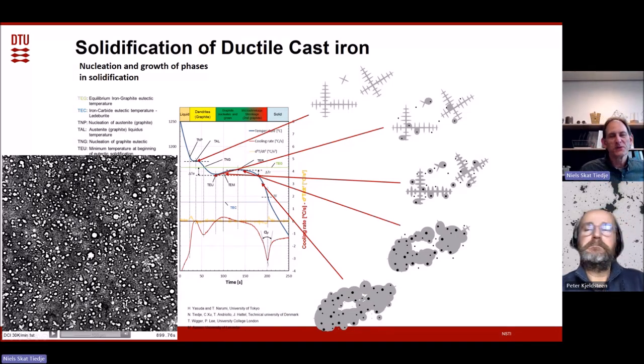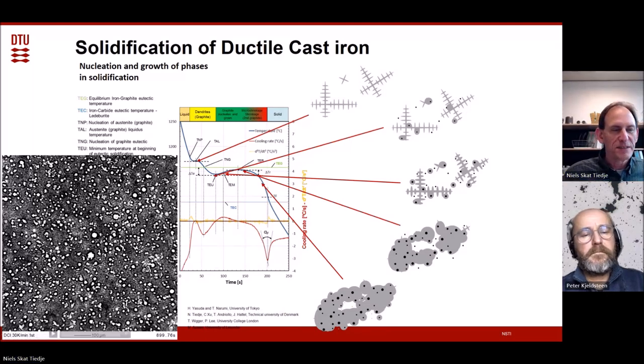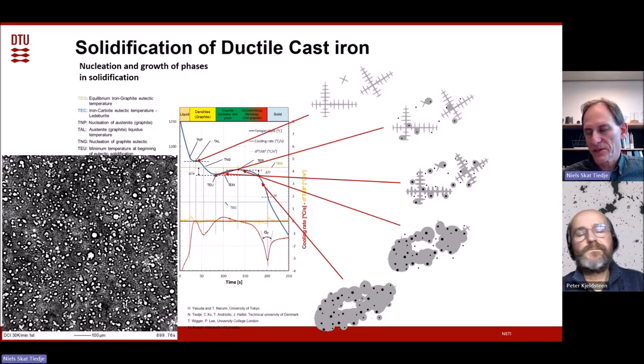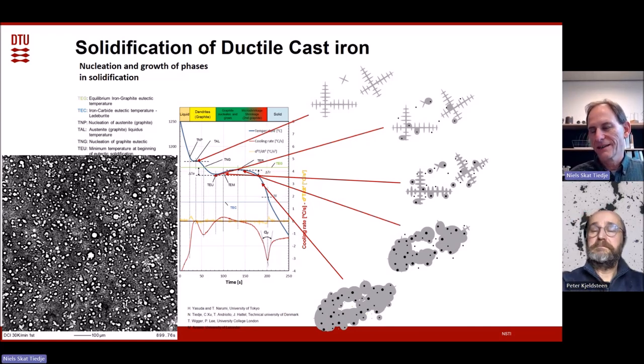And that comes back to the motivation for doing this. When you have success with this, it takes those 2-millimeter diameter cylinder samples. It took 3 or 4 months just to make the first sample that works. Then you have a week at the synchrotron where you work 24 hours a day. And we did maybe 20 or 25 experiments and 2 of them were successful, something like that. So you put so many hours into it. So when something finally comes out as a success, it's fantastic.